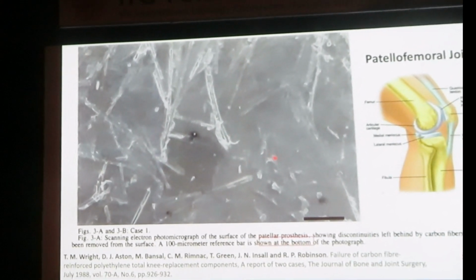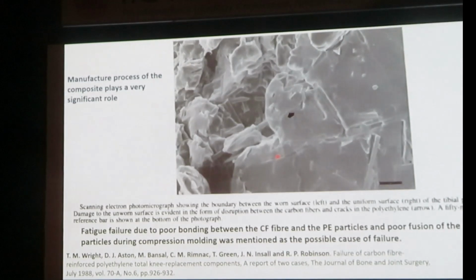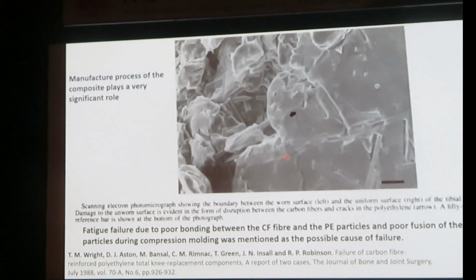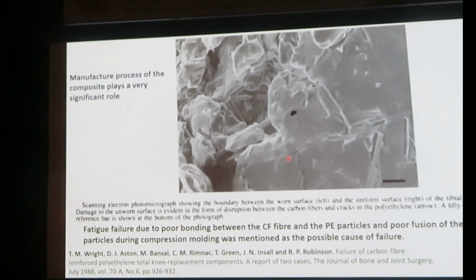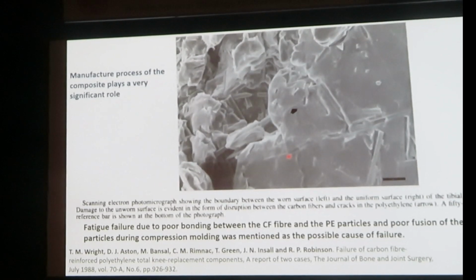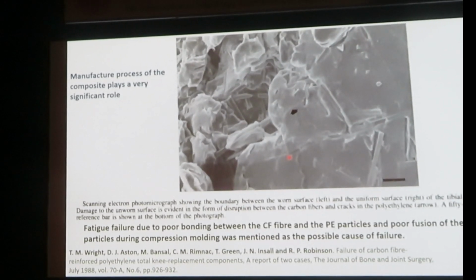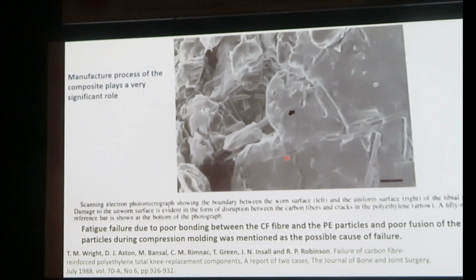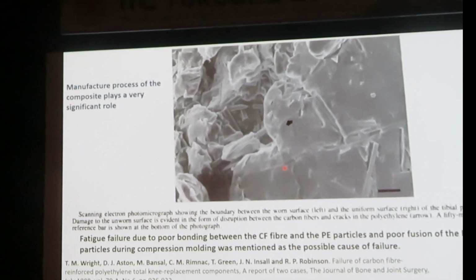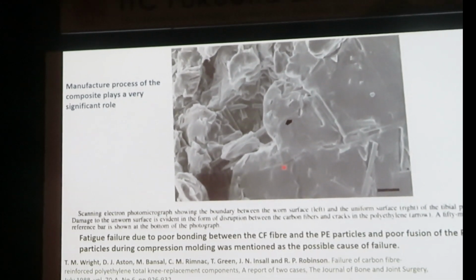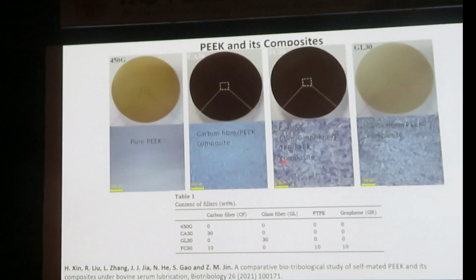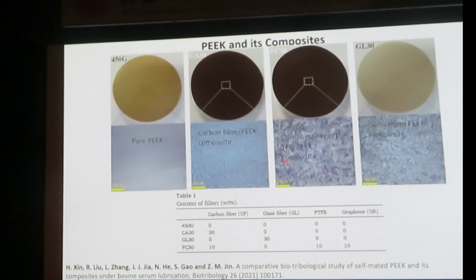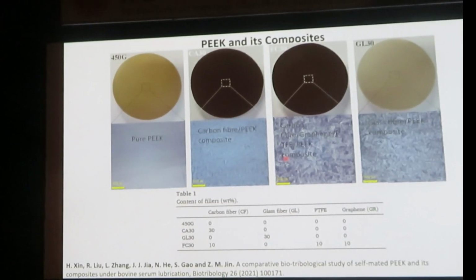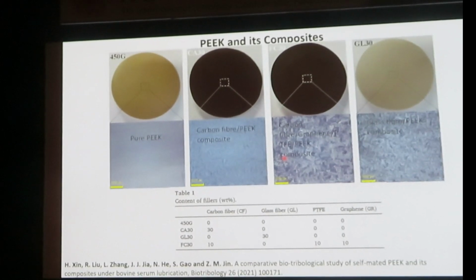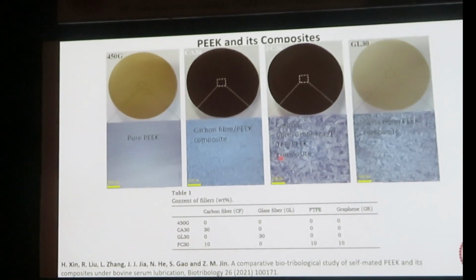This is quite well-known work now. The researchers found that the failure could have been because of poor bonding between the fiber and the matrix. So there is some scope that if we improve the bonding between the fiber and the matrix, perhaps that can help in the future. After this, I will move to PEEK, and its composites.